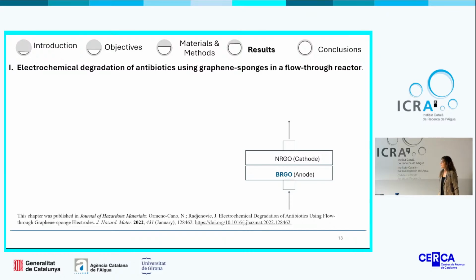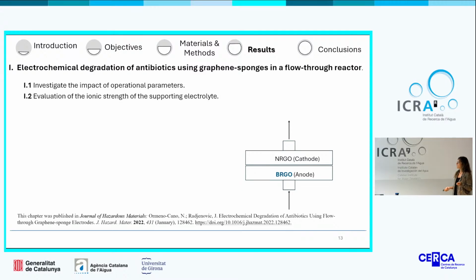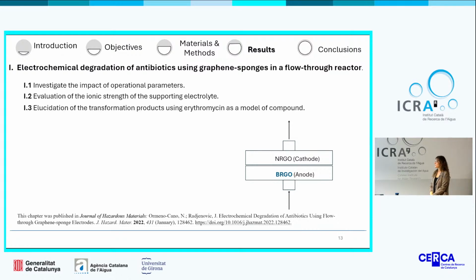In the first study, the electrochemical degradation of a set of 4 commonly used antibiotics using graphene sponge doped with boron was evaluated in a flow-through reactor. In the first point, we investigate the impact of different operational parameters. In the second point, we evaluate the ionic strength of the supporting electrolyte. And in the third point, we elucidate the transformation products of erythromycin as a model compound.